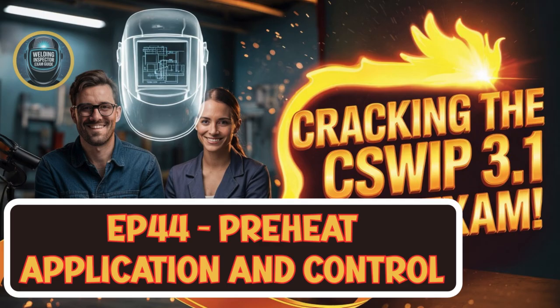Essential variables. Okay, that sounds pretty important. What does that mean in practice? What's the impact if someone just decides to, say, preheat a bit less or let the interpass temp drift too high? It's more than just important. It means you've basically invalidated the qualified procedure, the proven recipe for that weld. Any change outside the qualified range for an essential variable, like preheat or interpass temperature, requires a completely new procedure qualification test. Wow, a whole new test. Yep. Just for changing the preheat slightly. If it goes outside the permitted range, yes. It's not a suggestion. It's often a contractual and regulatory requirement. It ensures the safety, the quality, the fundamental integrity of that weld. Right. And by extension, the whole structure it's part of. You can't just wing it.